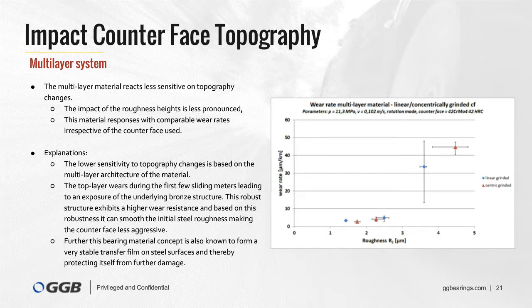We also know that these material concepts form a pretty stable and robust transfer film. And we know that such high quality transfer films help to effectively protect the bearing surface from damage by the attacking counterface.